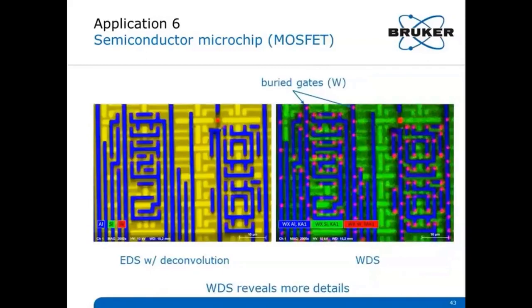Here are EDS and WDS maps of the same close-up on the microchip sample, showing a MOSFET transistor. Silicon in green, aluminum in blue, and tungsten, which is not shown here, make up the MOSFET structure. You can nicely see where the aluminum is, and it's in the same places as the tungsten, which we don't show here. And silicon, obviously together with some other elements, is found here in between.